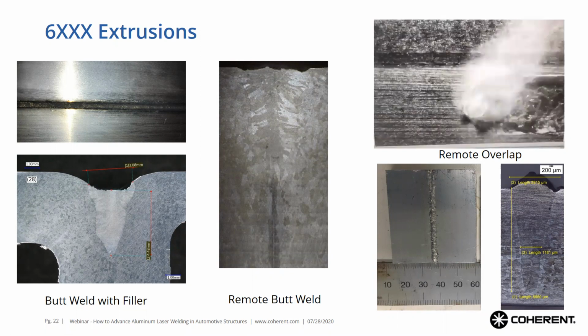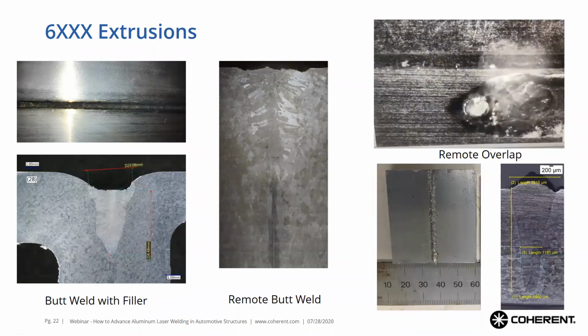However, you can see that there's actually not a ton of spatter being ejected out of the weld. The resulting weld is what you see in the bottom image. And we were able in this case to do a 5.7 millimeter deep weld in this overlap configuration, which is quite deep, and no cracking again, very little porosity. So very successful in extrusion materials as well.